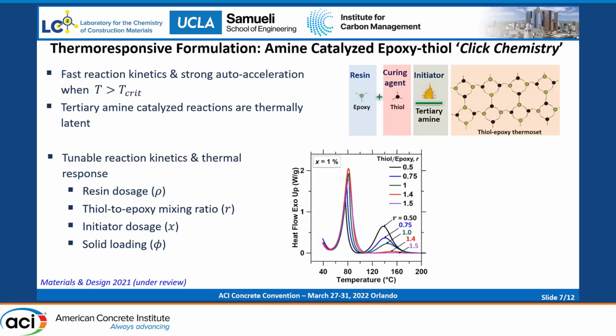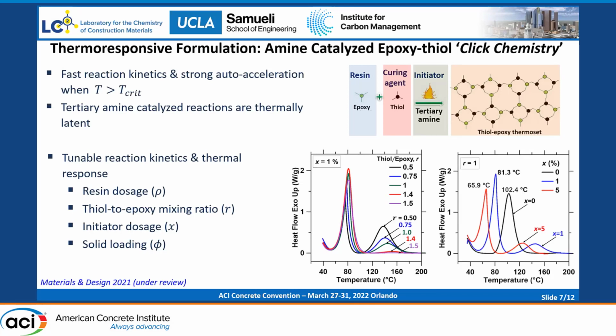This particular epoxy-thiol reaction controls the low temperature rapid stiffening, and this second reaction, the homopolymerization, provides the mechanical strength. So by controlling this epoxy to thiol mixing ratio, you will be able to either get a suspension which has a very high stiffening response, or by using some excess epoxy, you can compromise on the thermoresponsiveness, but you can get a good mechanical strength. And for another example of this formulation control, by increasing the amount of initiator in the mixture, we can bring down the activation temperature to whatever temperature that we want, something close to 60 or 50 degrees Celsius.